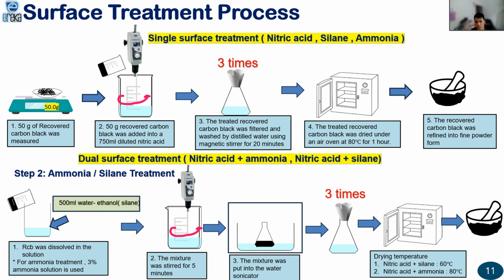However, if you want to use the dual surface treatment, we can use nitric acid plus ammonia. For ammonia, we can use ammonia solution, and for the silane treatment, we can use ethanol. So we will mix with the RCB, go through the mixing process, and then put it into the water sonicator. Then we need to filter the same way, and then the drying temperature differs for each type of surface treatment. Lastly, we will refine it into carbon black powder form.